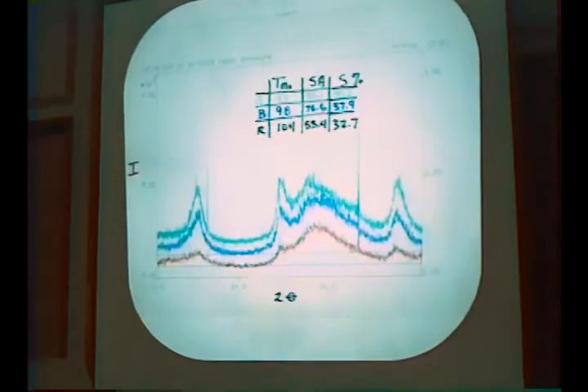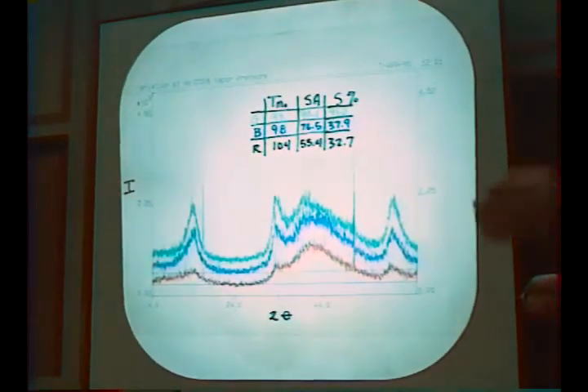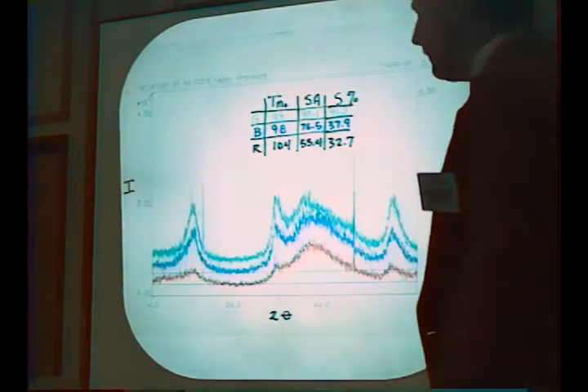Why is that? I think what we're making here, and I've seen in the XPS, is something lower valent than molybdenum disulfide. And so in this case, as you decrease the molybdenum temperature, you're actually increasing the molybdenum disulfide that's being produced. Or you're actually making more molybdenum disulfide as opposed to a lower valent compound. And that's how I would explain that. And I think that is borne out with the XPS data.